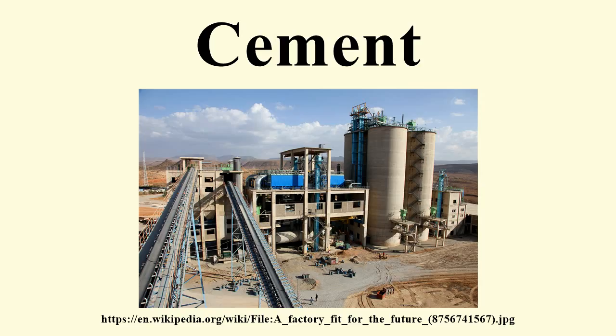Bertrand H. Wait, an engineer whose company had worked on the construction of New York City's Catskill Aqueduct, was impressed with the durability of Rosendale cement, and came up with a blend of both Rosendale and synthetic cements which had the good attributes of both. It was highly durable and had a much faster setting time. Mr. Wait convinced the New York Commissioner of Highways to construct an experimental section of highway near New Paltz, New York, using 1 sack of Rosendale to 6 sacks of synthetic cement. It proved a success, and for decades the Rosendale synthetic cement blend became common use in highway and bridge construction.